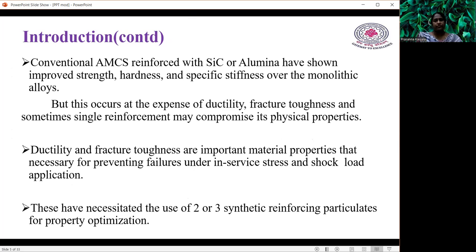Basically, here we want to improve the strength and the hardness, while not compromising the ductility and the fracture toughness. So an optimized value has to be found out. We have done that through the Taguchi technique, where we took many parameters and varied some of the values, and then we could find the signal to noise ratio. Finally, we could get one optimized value. This is all around the wear loss. We are trying to minimize the wear loss, and we are trying to introduce the graphite for good lubrication purposes. These have necessitated the use of 2 or 3 synthetic reinforcing particulates for proper optimization.